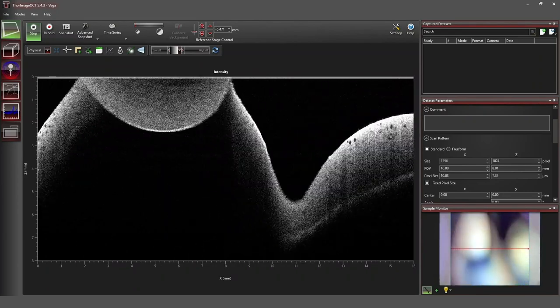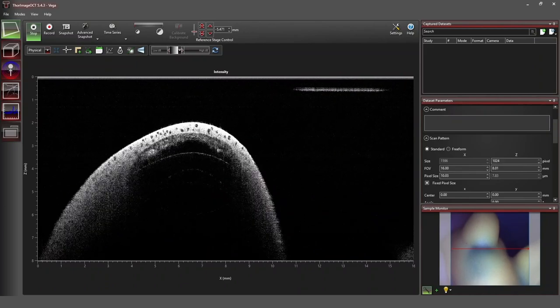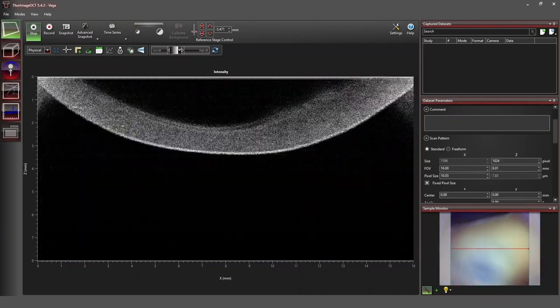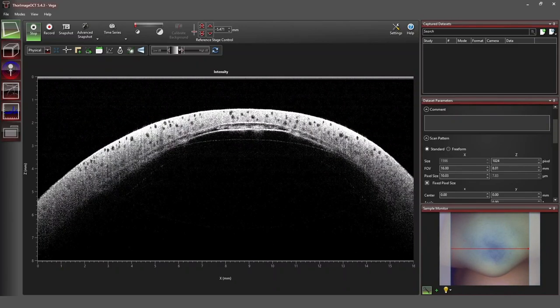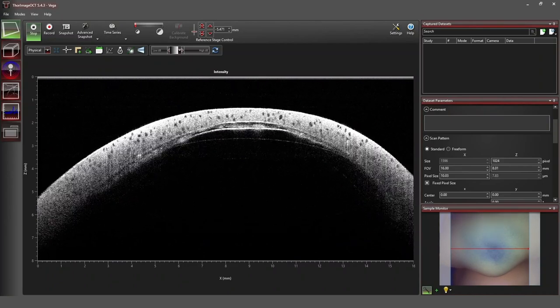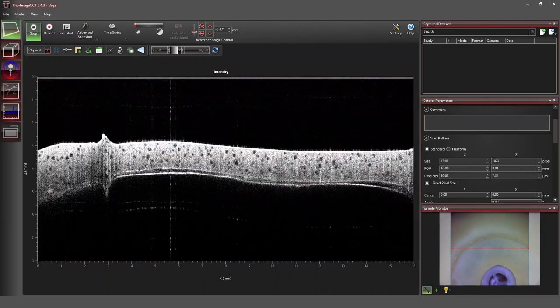But when we move on to the wing, we suddenly see that below the inner surface there is something appearing. And when we move on to the tail — now look at this — we can see this even more clearly. From top to bottom we can see the top surface, then some microstructuring within the rubber material with all these black spots, and below the second interface there is something different — probably a biofilm that started to grow because Daisy stayed wet after some swimming lessons. And now looking at the bottom, we can clearly see a biofilm forming on the inner surface of Daisy.